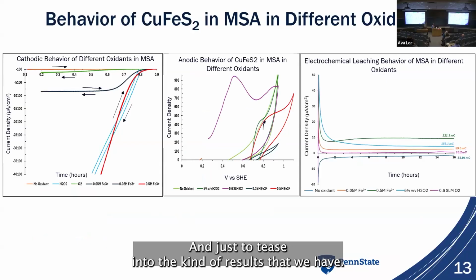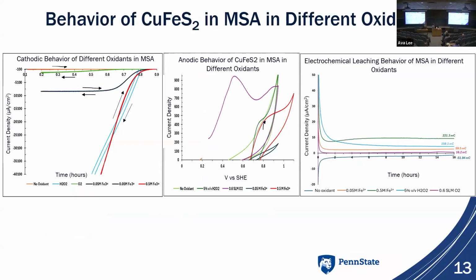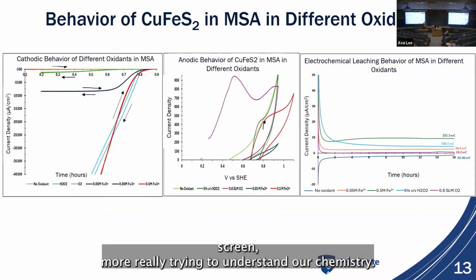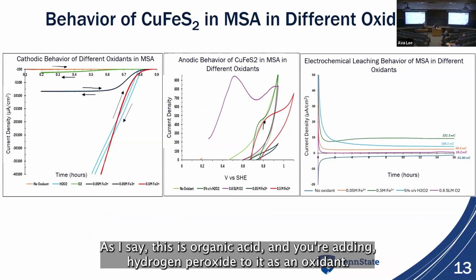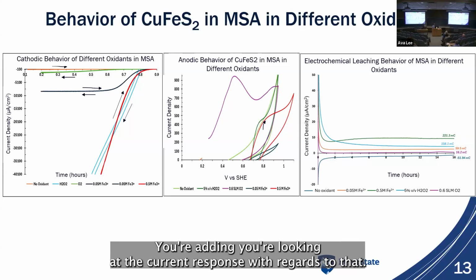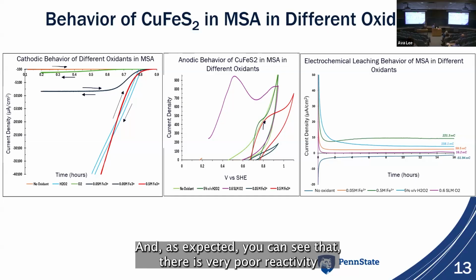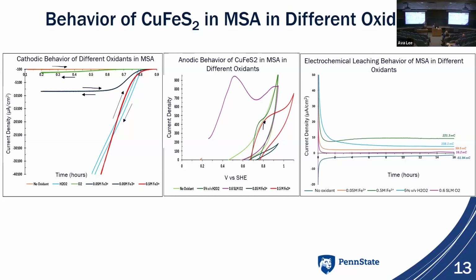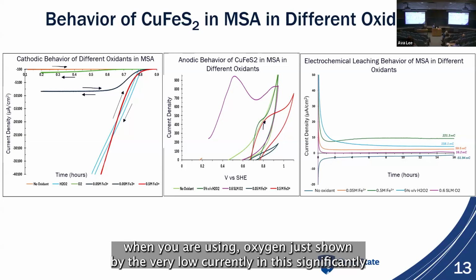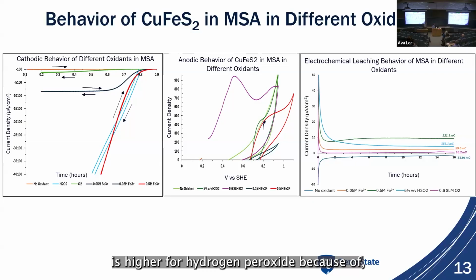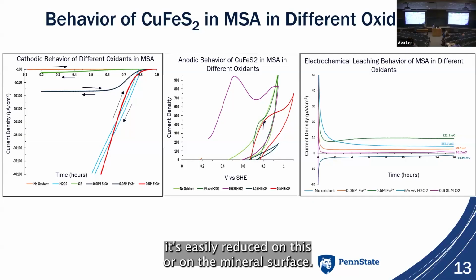And just a tease into the kind of results that we have. What you see to the far left of your screen is really trying to understand our chemistry. As I said, this is organic acid, and you're adding hydrogen peroxide to it as an oxidant. You're looking at the current response with regards to that. And as expected, you can see that there is very poor reactivity when you're using oxygen, shown by the very low currents there. And this is significantly higher for hydrogen peroxide because it's easily reduced on the mineral surface.